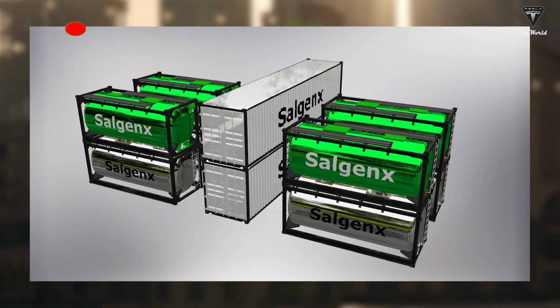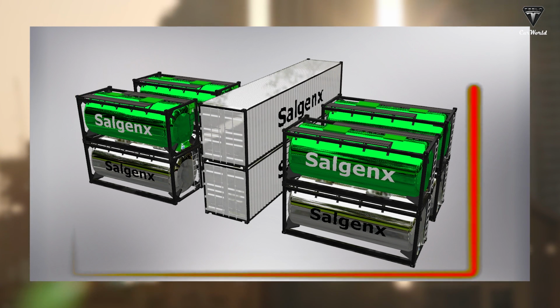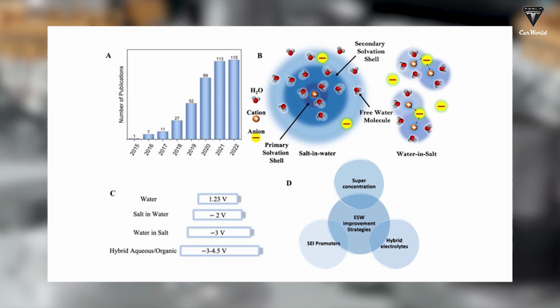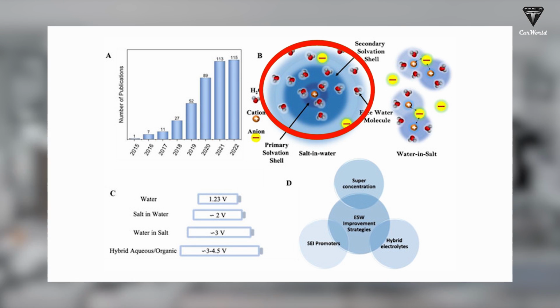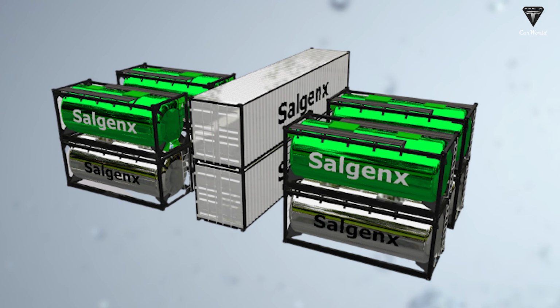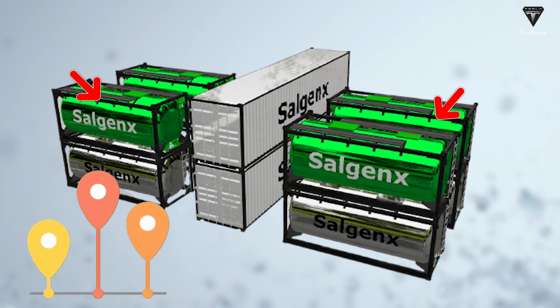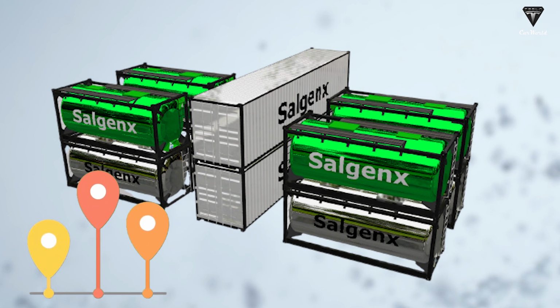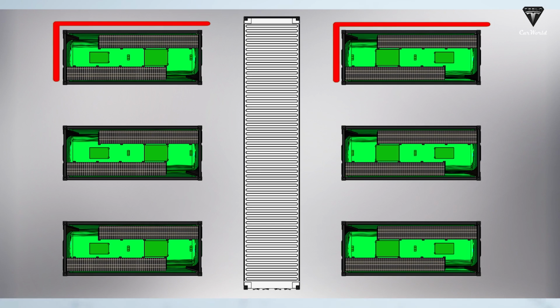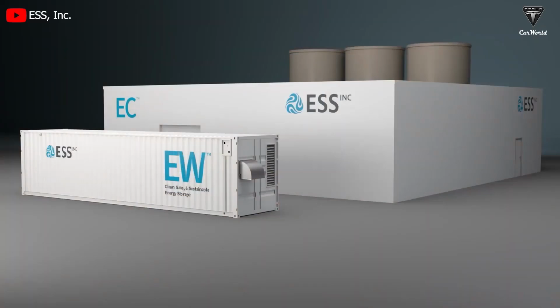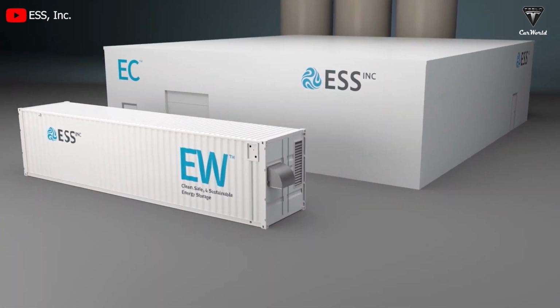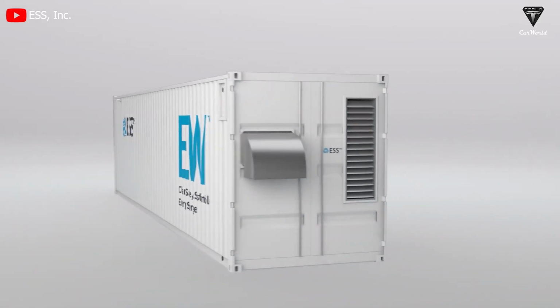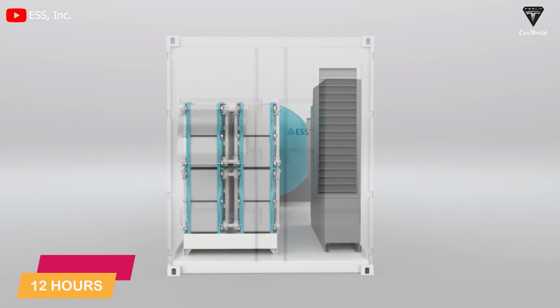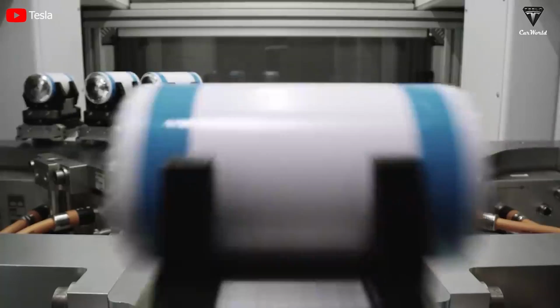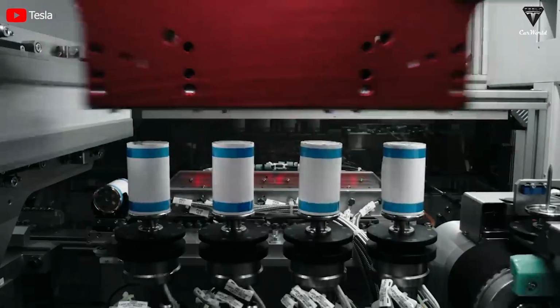Based on its simple design, saltwater batteries offer direct control over their energy and storage capacities as long as it has enough electrolytes. It can theoretically increase the storage as much as you want by increasing the size of the tanks. And if the number of the electrode cell stacks are increased, that means more power. ESS announced that the maximum storage duration mark of their iron flow batteries is 12 hours, which remains greater than lithium-ion batteries at 30 minutes to 3 hours.